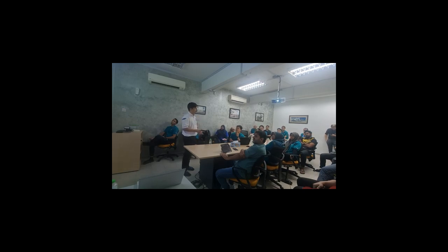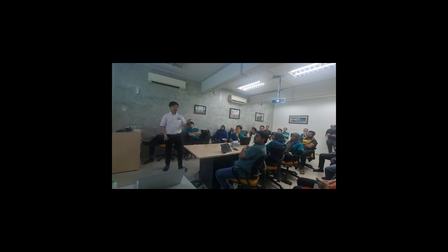Some are like a flowery shape. Some from flower actually expand back to the normal shapes, the comb shapes. So there are a lot of possibilities with PCE. You can actually change the shape of the polymers to customize to what you want. Like for early strength, maybe you want a shorter side chain to enhance the early strength.